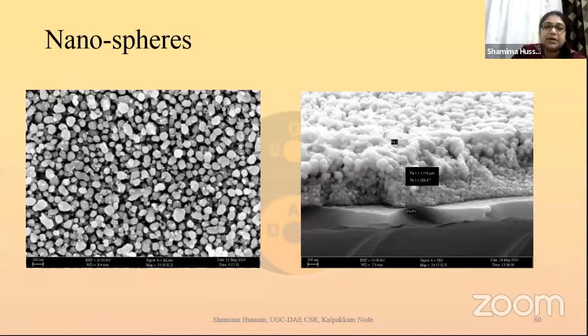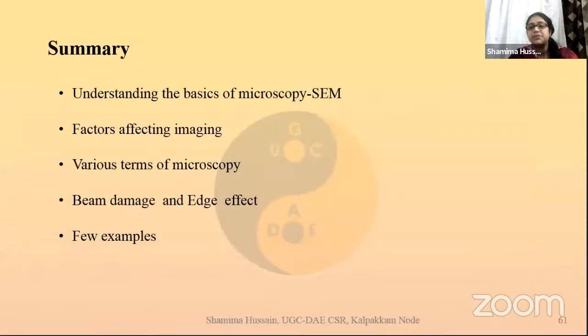Now for this particular micrograph, I will be drawing many such squares, and then I'm going to just make the average. So that's what I said, that when we get the curve, we will see that in one square I would have had 50 particles, or the average particle size was 50 nanometers. In another, I might say 40 nanometers. So what do I do when I get many such squares on my micrograph? I'm going to make an average of all of them, and I might report that the average particle size was 45 nanometers.